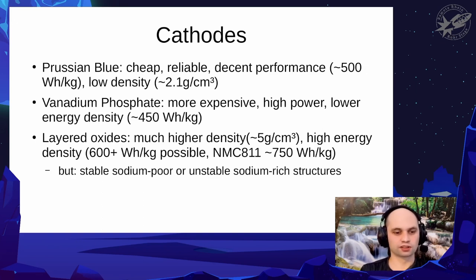And usually, with a lithium ion battery, you have all the lithium inside the cathode of the battery when you build it, and then you just charge it and move the lithium over to the anode side. When you want to use these sodium-poor and very stable materials, then you need to get your sodium from elsewhere. Either you already have it on the anode side, or you put it into some other material. And research has been going on to put it into all sorts of things.